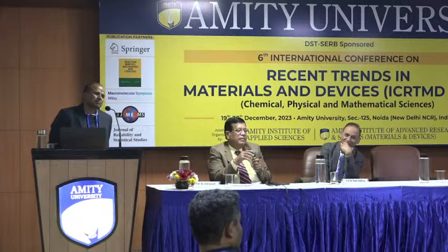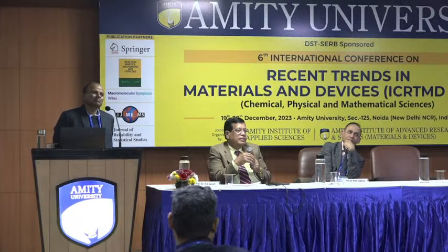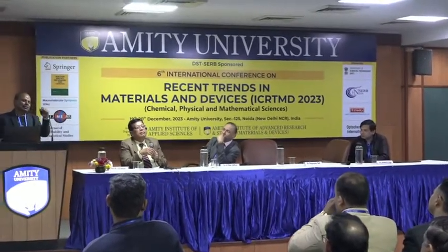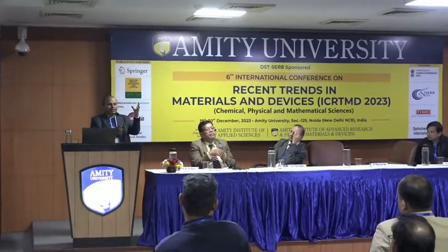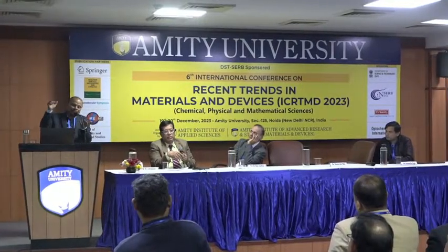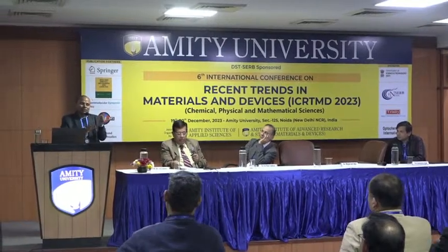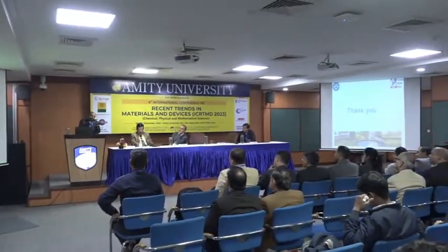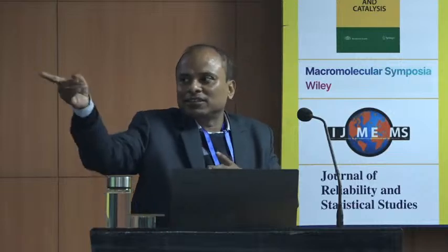One thing, sir, you have mentioned superoxide, and you have shown some data. You showed that if you have more superoxide in a sample, it is giving you more product. Actually, ceria is a redox catalyst, so it can absorb oxygen and it can remove oxygen. What we found is that if you make ceria 3+, if you reduce that, automatically an oxygen vacancy is created. That oxygen vacancy can be filled by molecular oxygen. That molecular oxygen can dissociate on the vacancy site and make the superoxide species. That means oxygen can be easily available for the reaction. So what we found during DRIFTS, IR and Raman is that this type of species can be found in this catalyst, and they can give you more product. Yes, a more active oxygen species, we can say.